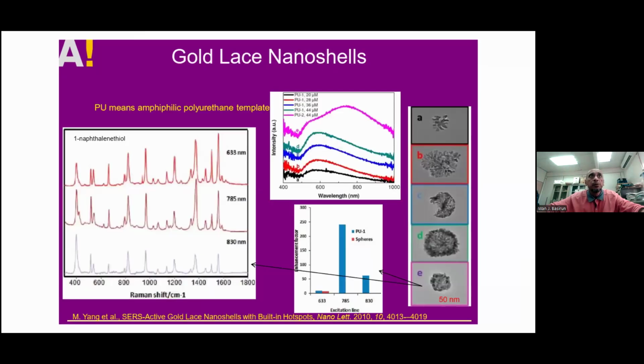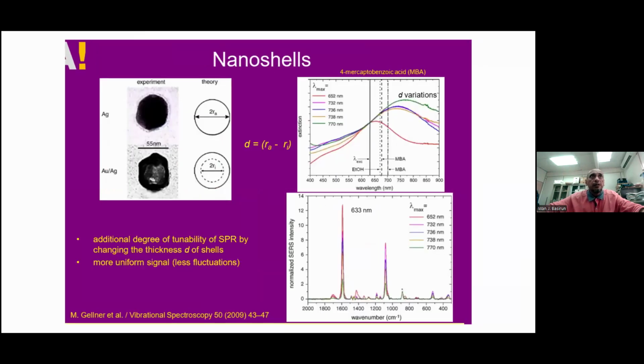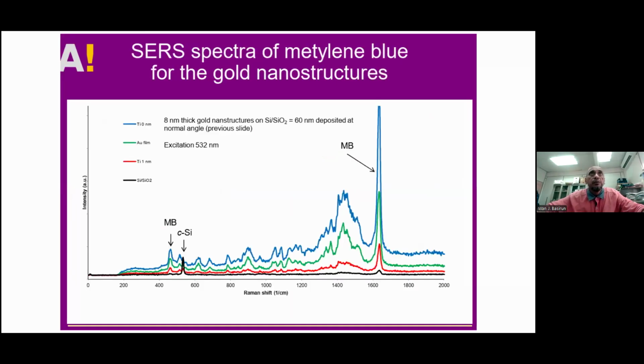Okay, and also gold nanoshell or gold nanoparticle with the organic compound. Okay, we observe this spectrum. Okay, and a nanoshell, for example, a silver and gold silver core shell structure in nanoparticle. So as long as this gold surface bonds with the analyte, then you can observe the SERS effect. And also like methylene blue absorbed onto gold nanostructures. So these are all typical sample preparation of gold and organic compound. As long as the gold bonds with the functional group of the organic compound, then you can observe this SERS effect. Okay, so that is a summary.